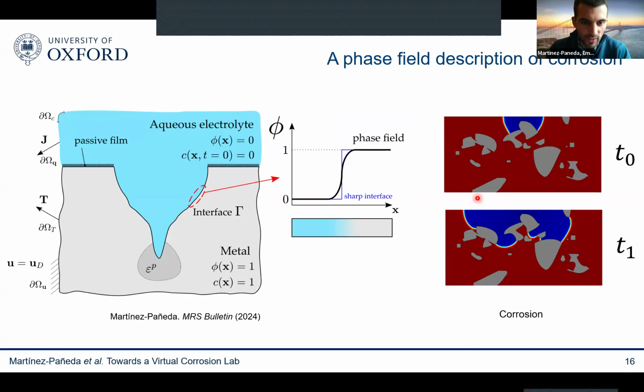So how does it work? Again, I'm not going to get too much into the details. I summarize a little bit the state of the art in this recent review paper. But the idea is that, similar to other interfacial problems, the phase field is going to describe the evolution of the corrosion front. So the phase field is going to describe material dissolution. So it's going to be equal to 0 in the aqueous electrolyte, equal to 1 in the metal, and then varying smoothly in between. So now we have that concentration and that phase field variable.